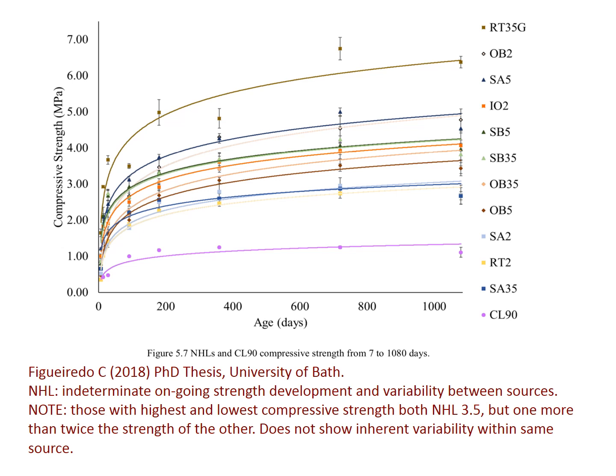The lowest line there, of course, is the air lime control mix, which wasn't hot mixed. And we see that the weakest on test was an NHL 3.5, but also the strongest on test was an NHL 3.5. In several cases, the NHL 2s were stronger than the 3.5s or the 5s, and so on. This is a variability between brands that is intolerable unless the specific brand is specified, not just the number. Of course, the other main thing being shown here, and this is after 3 years, is indeterminate ongoing strength development. And we don't know when this stops. There is no one who can tell us when this stops.